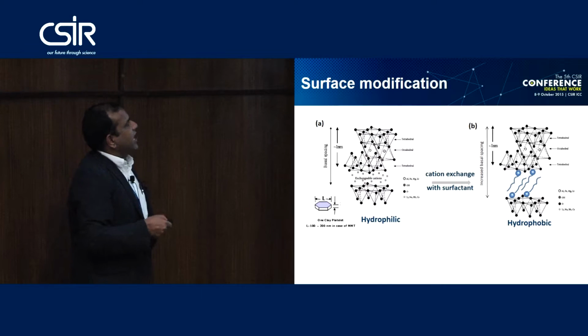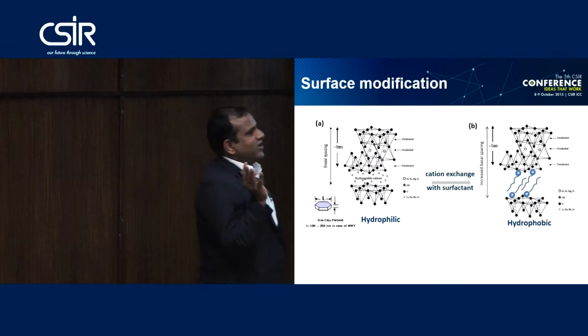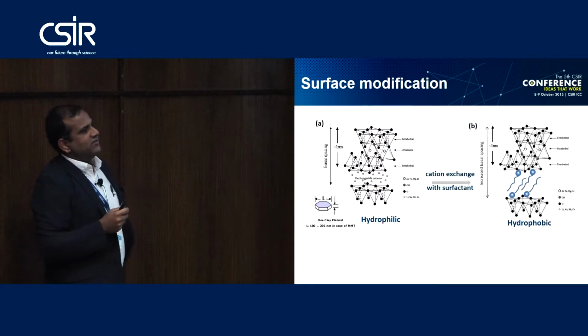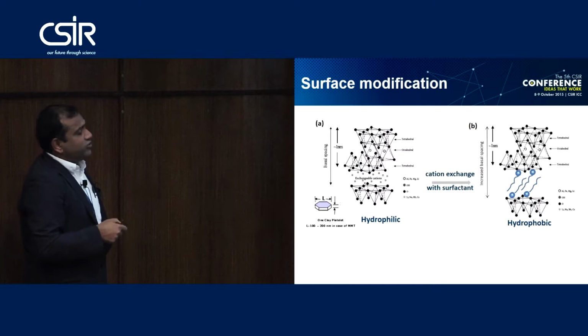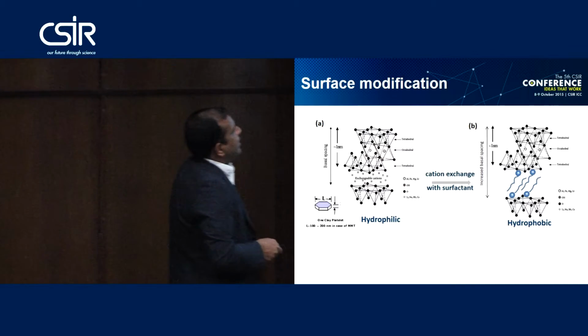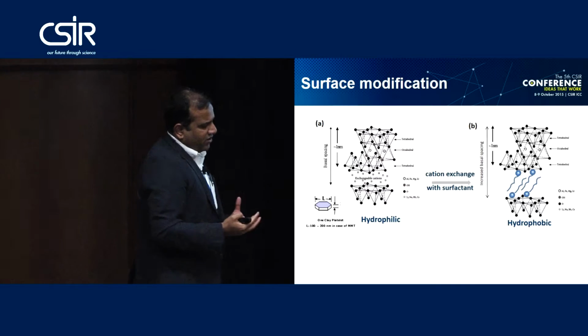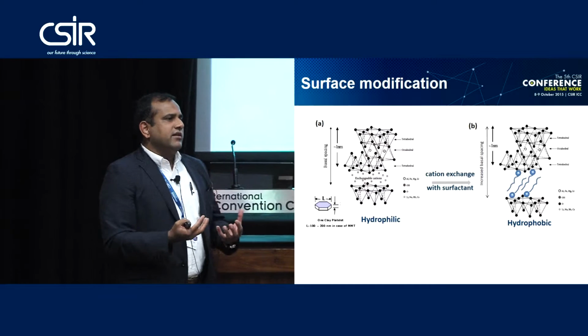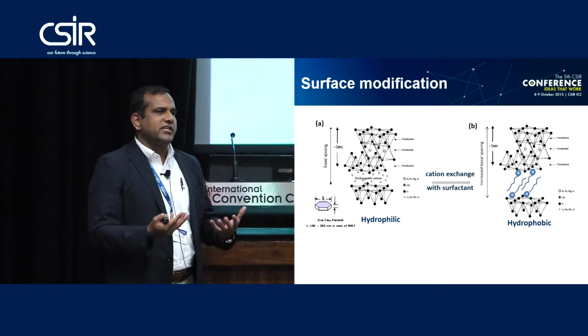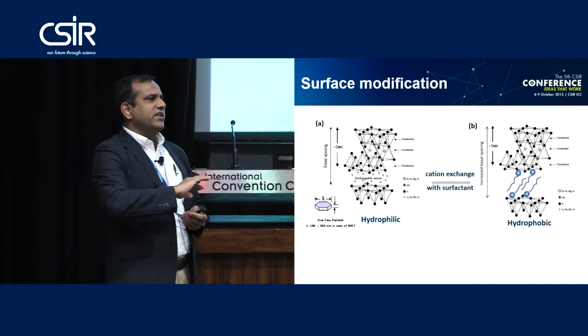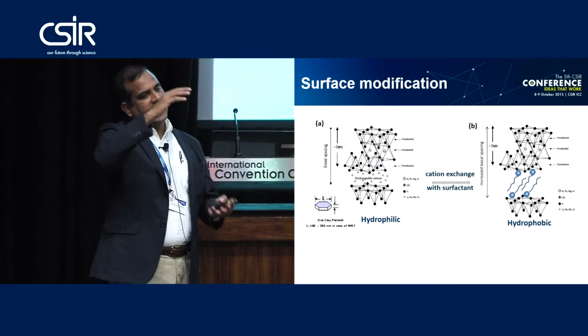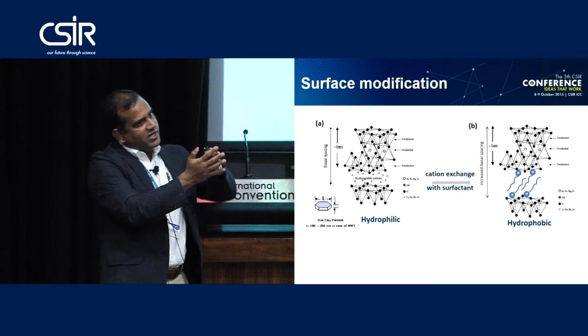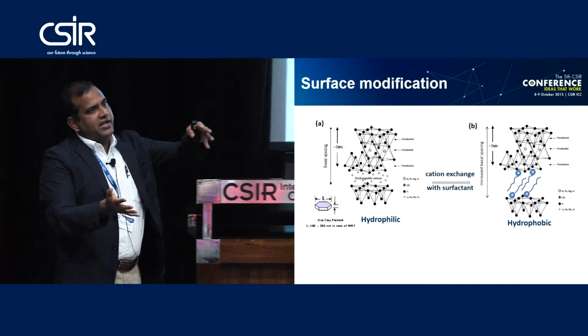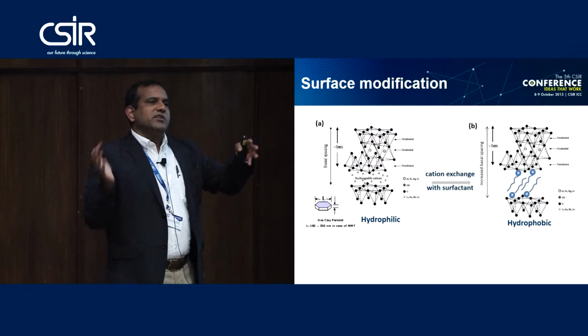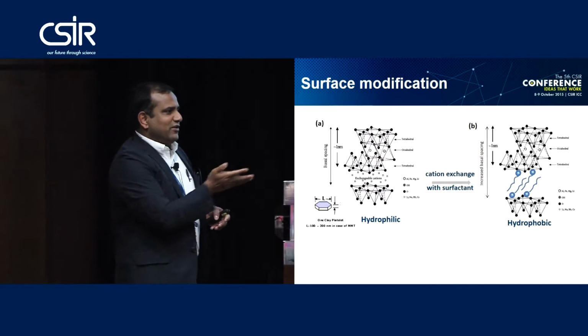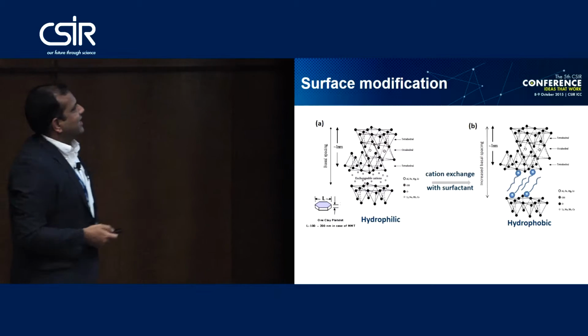And what we are doing, if you come to building 23, there is a huge plant. We are doing scaling at almost the 100 kilogram level. We are converting, through a simple ion exchange reaction, hydrophilic clay to an organophilic one. And what is the benefit of that? There is a twofold benefit. When you replace the sodium or interlayer cations by surfactant, you convert the surface from hydrophilic to hydrophobic, and at the same time, because the size of the surfactant is much larger than small cations, you expand the gallery between the two platelets. You need that expansion because your macromolecular chains must go inside that gallery to have an intercalated structure.